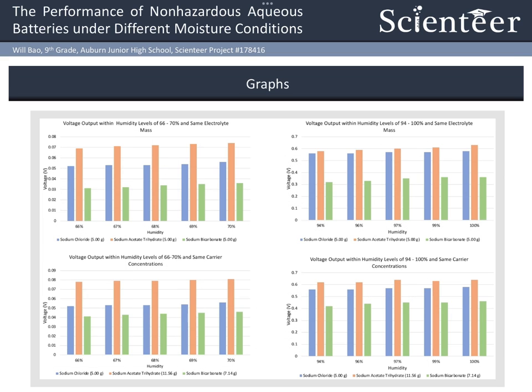As you can see, there are 2 sets of data, with one having the same mass for all 3 types of electrolytes, 5 grams, and the other having the same carrier concentration, which just means that there are the same amount of charged particles. The sodium acetate trihydrate, which is the orange bar, had the best performance out of the 3 types of electrolytes in all scenarios, and its voltage output was boosted even further when the humidity was around 94 to 100%.